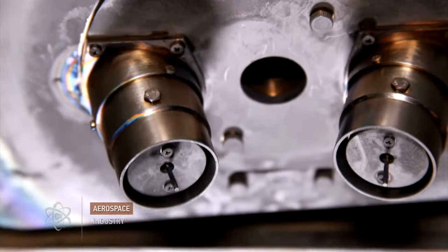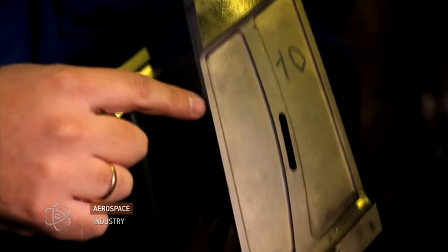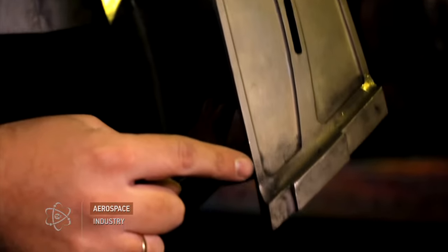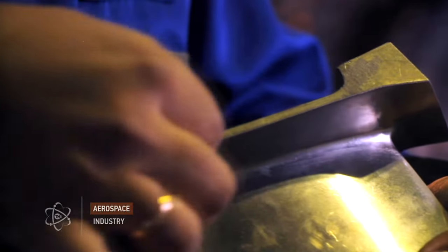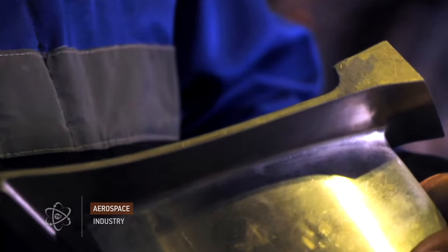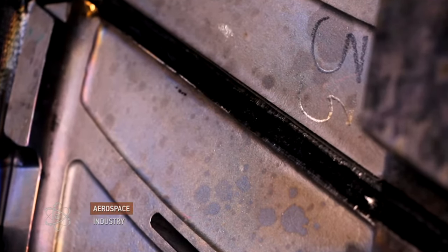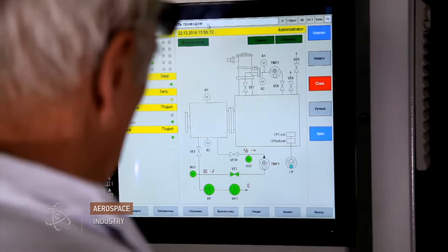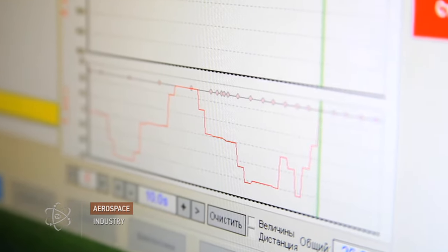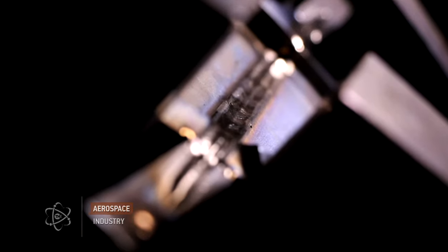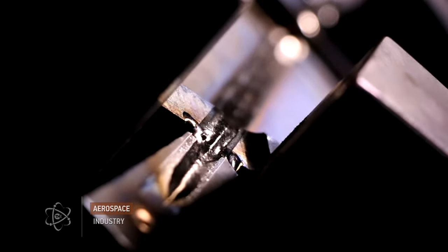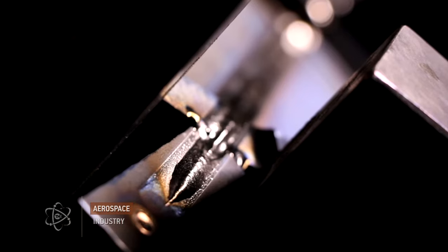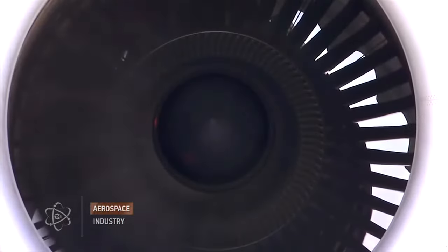The developers faced 2 problems while making the welded structure. 1. Geometrically, the joint was a variable cross-section. 2. The through penetration weld had to be 5 to 25 mm thick and made in one run. Scientists of the E.O. Paton Institute found effective solutions to both problems. The process is entirely controlled by special software, and the welding program excludes an operator. The welding factor of joints conforms to the strength factor of the metal body.